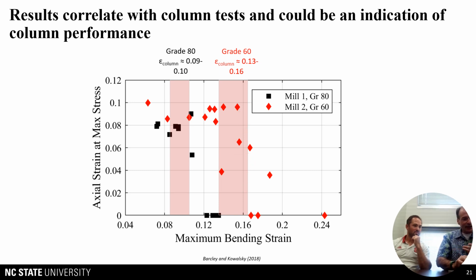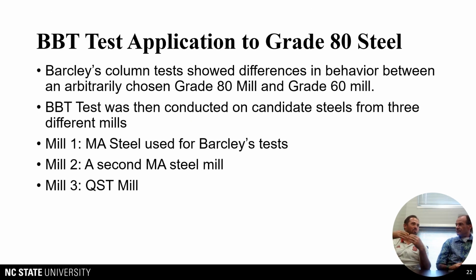So it's a little bit to the higher side of that purple or reddish band where that's matching up. But that we could get it to match up that way was quite interesting. The buckle bar tension test on the MTS machine was able to replicate the behavior of the columns, which then led us to think, well, this is the actual behavior of the buckled bar. It's not getting to its actual critical strain for elongation and then fracturing ductilely.